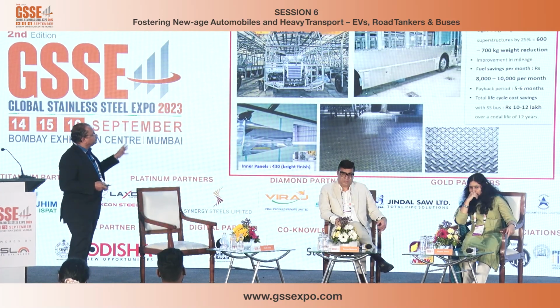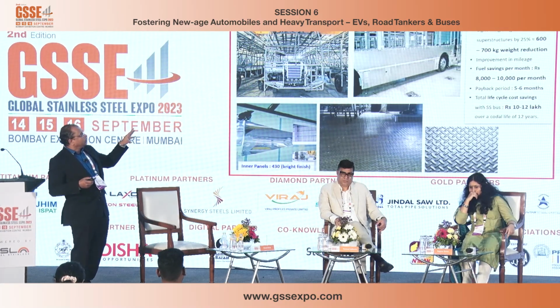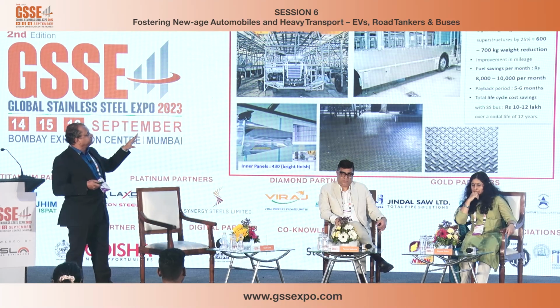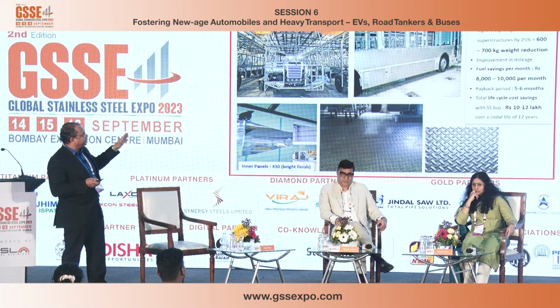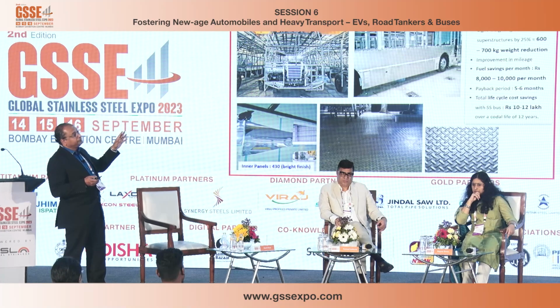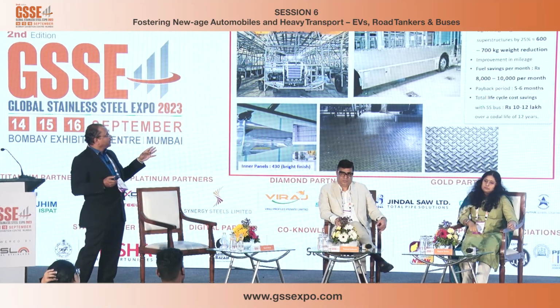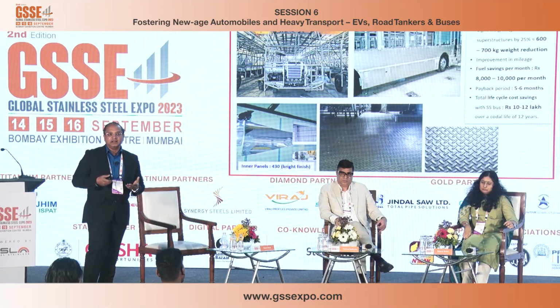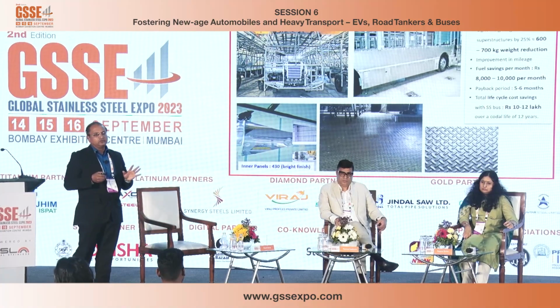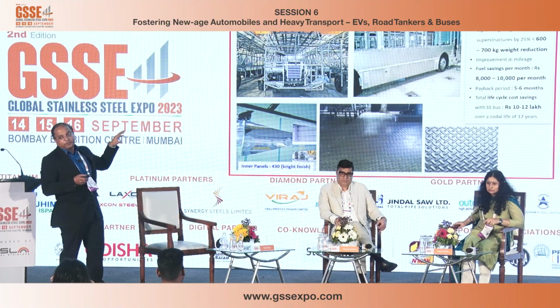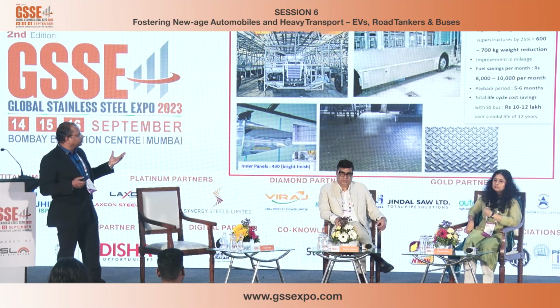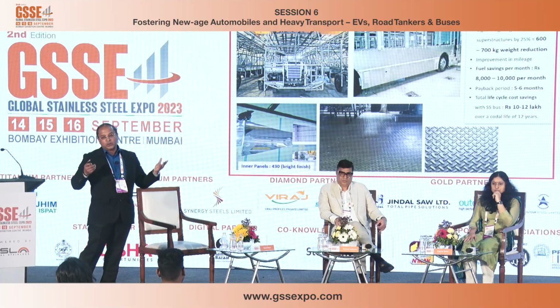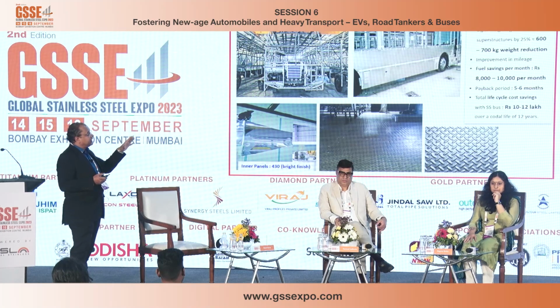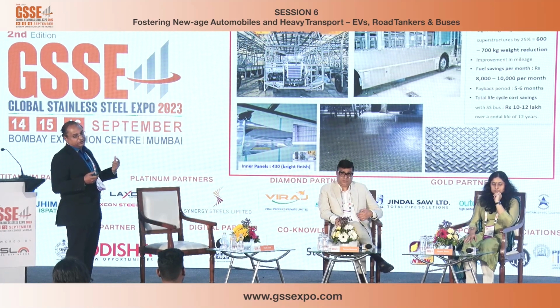So some examples. We did a lot of case studies, and what came out from across all those case studies was that if you are able to reduce the superstructure weight by almost 600 to 700 kg, then the fuel savings, at the current rate, come to about 8,000 to 10,000 rupees per month. The initial increase in the cost, because stainless steel is a costlier material as compared to GI tubes, comes to roughly about 50,000 rupees. And therefore, within a period of 5 to 6 months max, you can recover the cost. And then, over the life cycle of 12 years, that's the life which is considered in India, the savings is almost 10 to 12 lakhs per stainless steel bus.